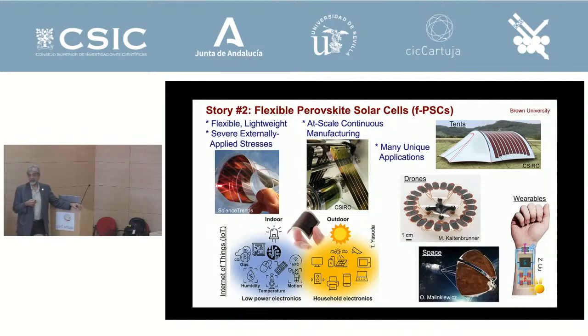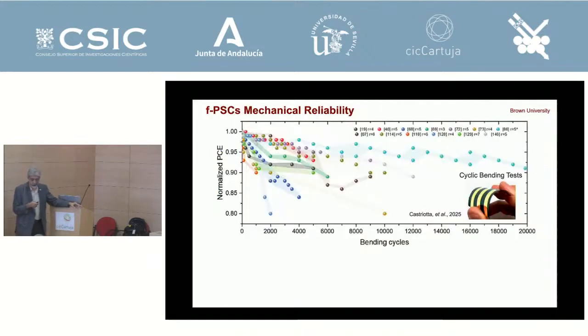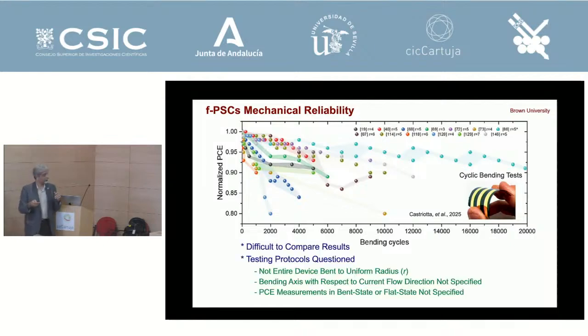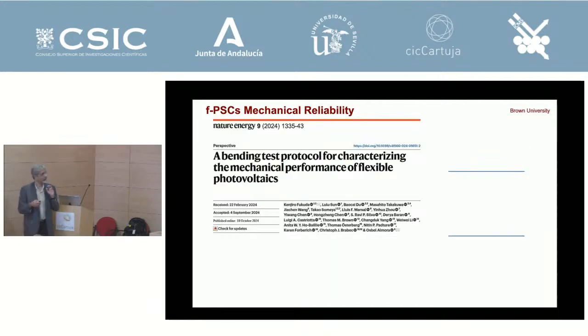And then space, so you can basically, like an umbrella, you need large area, you cannot take this big umbrella in a rocket, so you basically take it as a closed umbrella and then you unfurl it in space, and it has to be flexible, of course, right? And collect a lot of light. Anyway, so a lot of people do the testing by bending this, okay? So the mechanical testing of this is done by bending many cycles, and basically people plot the remaining power conversion efficiency as a number of cycles and say that this is fatiguing. But there's a lot of problems here. I won't go into the details here, but the tests are not conducted properly, and this cannot compare very well. And therefore I got involved in this consensus statement and by many authors.